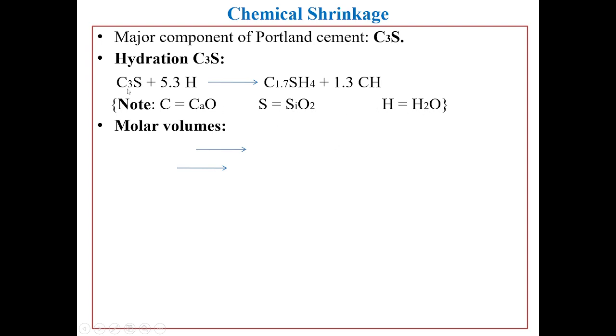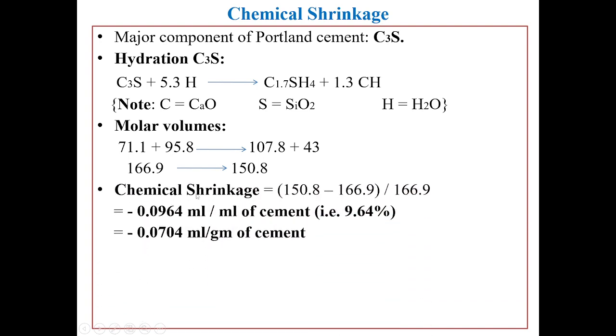So when I substitute molar volumes in this equation, it is 71.1 for C3S, 95.8 for 5.3H, 107.8 for C1.7SH4, and 43 for 1.3CH. So when I add this, it becomes 166.9, and when I add this, this becomes 150.8. So these are molar volumes. Now chemical shrinkage is nothing but final volume minus initial volume divided by initial volume. So when I solve this, I get minus 0.0964 ml per ml of cement. That means approximately 9.64%. And you have to concentrate on one thing, that the answer is negative.